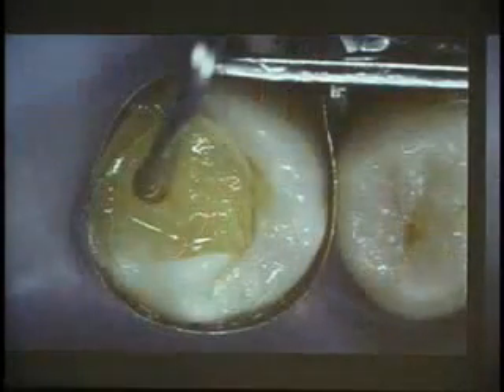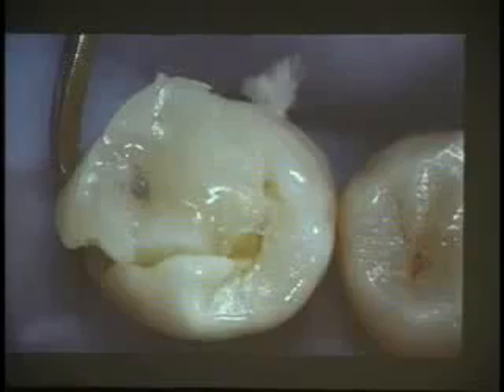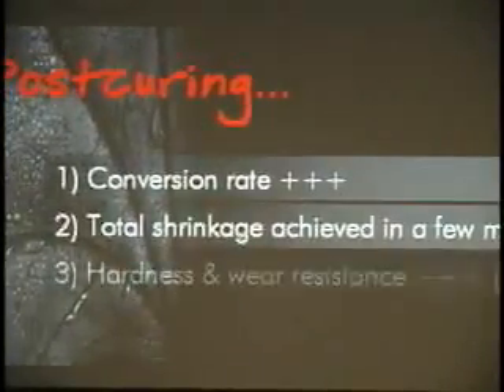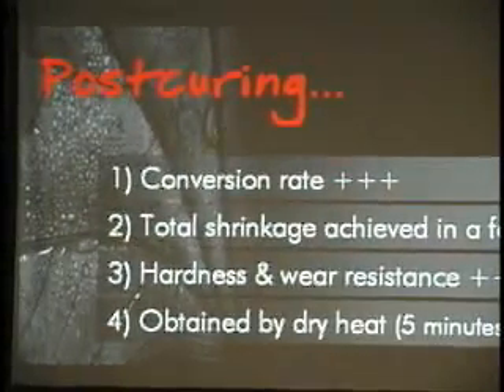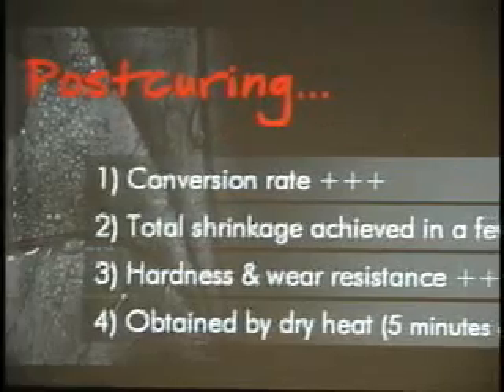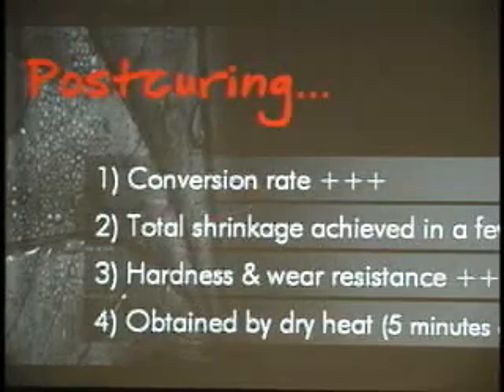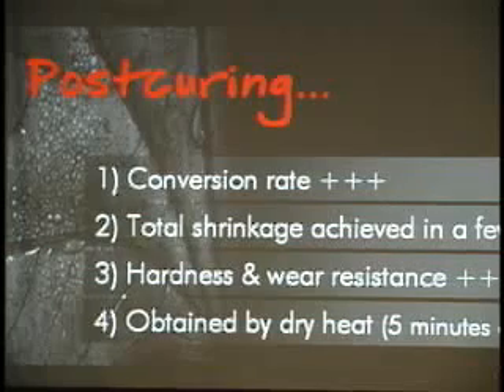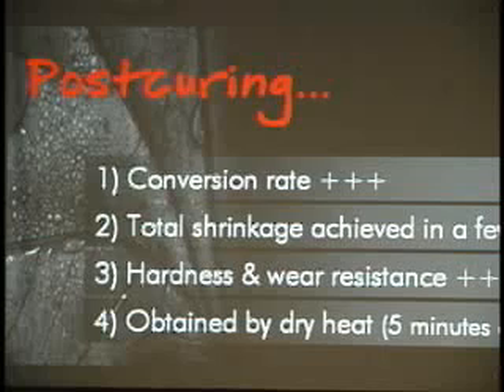So in that case, I was using Vaseline as a matrix, building up my composite directly in the mouth, then popping off the restoration and doing a post-curing process, because at that time we also believed that the conversion rate of the material would be improved. The total shrinkage would be achieved in a few minutes by this heating process, about 5 minutes at 100 Celsius, which is 212 Fahrenheit. We knew that hardness and wear resistance would be improved, at least demonstrated in vitro.